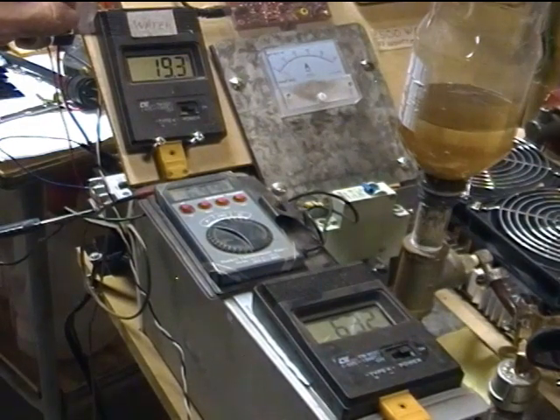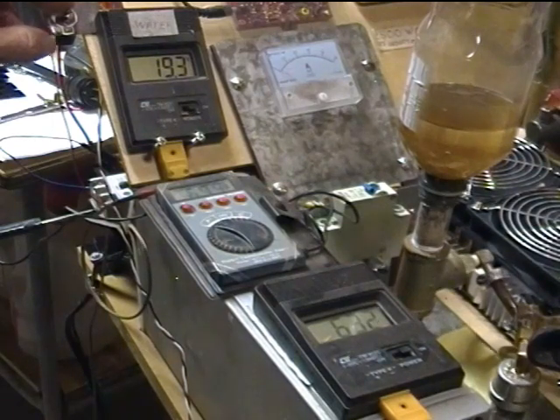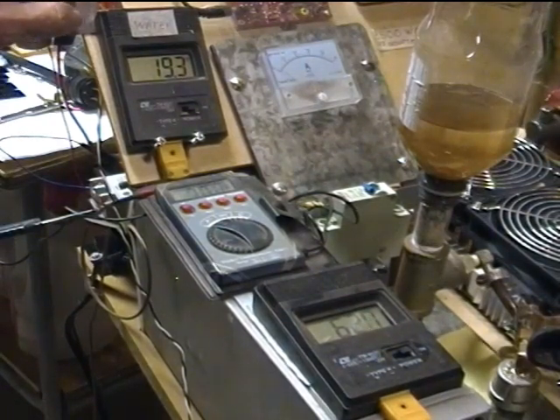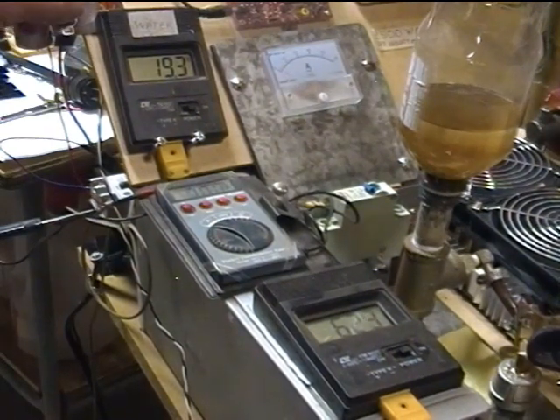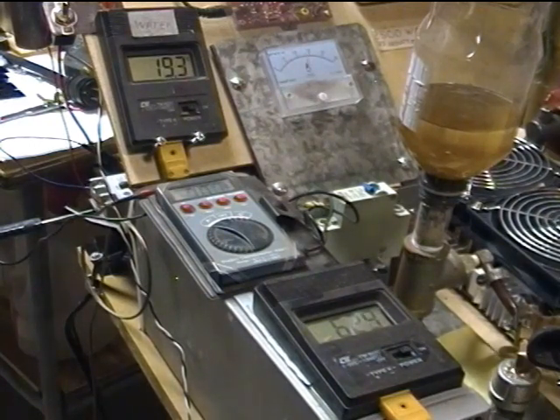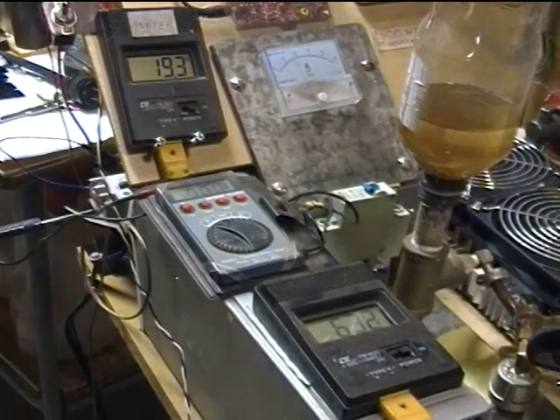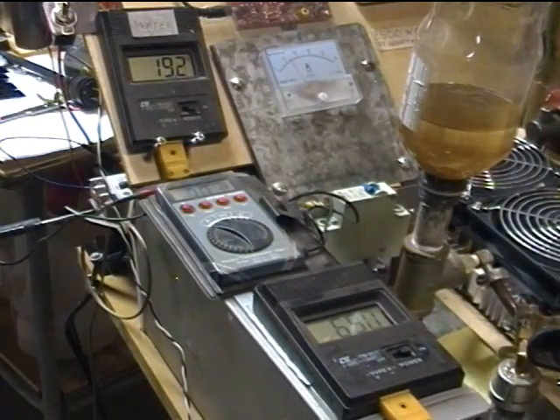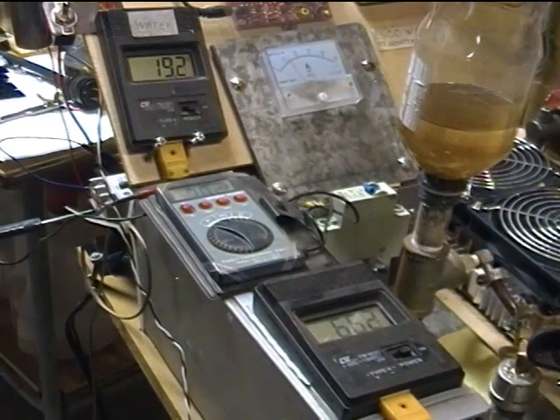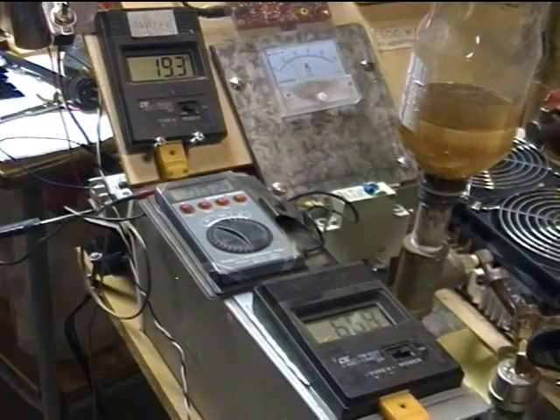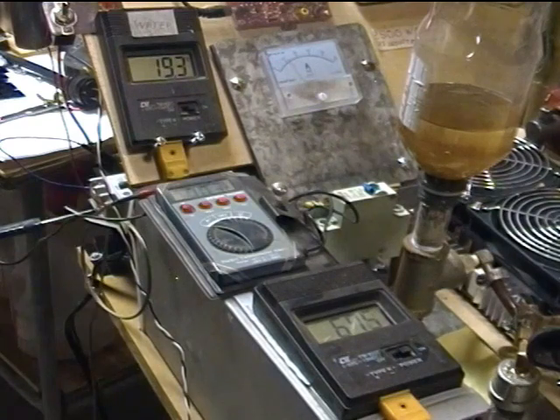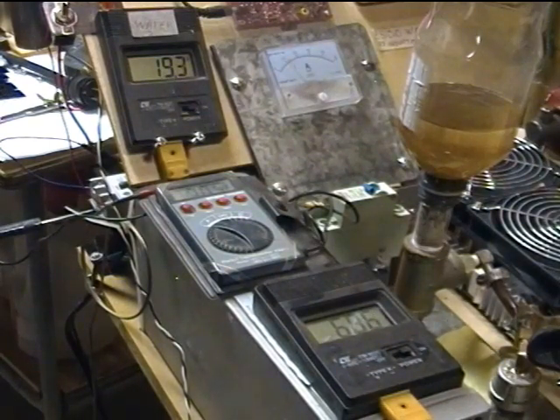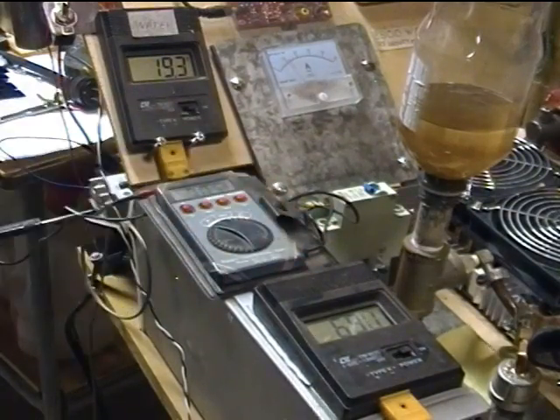I really don't think that leaving it on for a long time is that much of an issue. So at any rate I would declare this a success. Let's just leave it on for a little bit here. I know we'll go through the curie point. And where are we going to stabilize? It looks like about 14 amperes minus the idle current of 6. We're only putting about 8 amps at 50 volts roughly, 400 watts into the work coil which is sitting in a crucible. And now it's down to 12 amps.